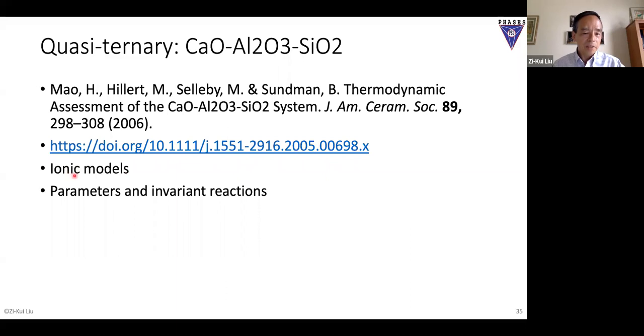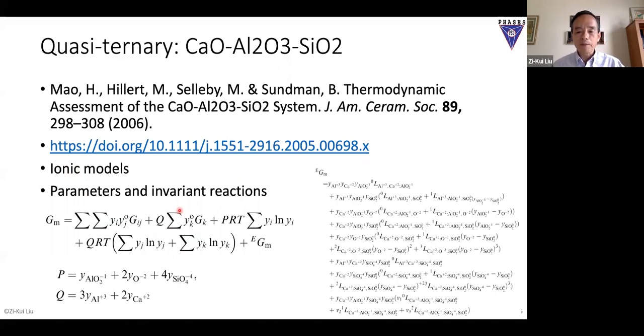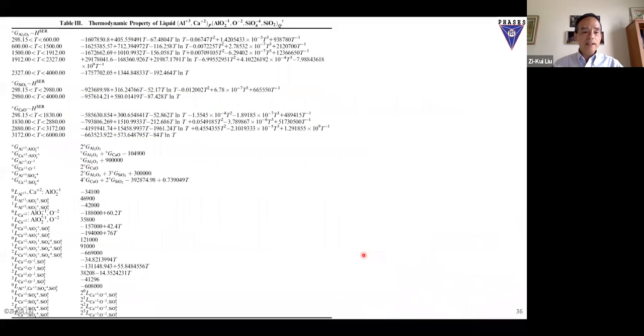And again, you have the ionic model, you have the parameters, and the invariant reaction. Of course, now it's more complicated than the binary system, but you still have the three major terms: you have the energy with the end members, you have the entropy, you have the interaction, you have the neutrality. And now this is the liquid equation, for the excess energy of the liquid phase in the ternary system. And then you can use the parameters.